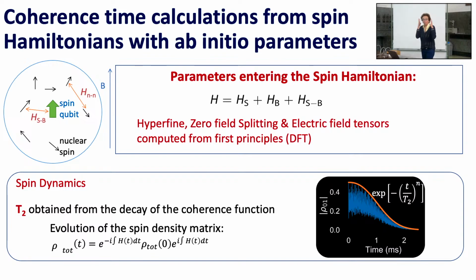So you have done all your electronic states. You then compute spin Hamiltonian parameters like hyperfine, zero field splitting. You set up your Hamiltonian. You do a dynamics. If you look at this for a minute, you immediately realize that this is not solvable like this, so you need to do some approximation. We can talk about this. And then you look at how it decays. This tells you how long your states will stay there before the interaction with the nuclei destroys everything.